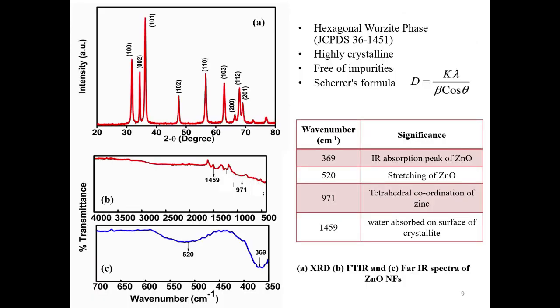This is the characterization technique we have used for the characterization of zinc oxide nanoflowers. We have done XRD. Here is the hexagonal wurtzite phase, which can be confirmed from JCPDS 36-1451. The material is highly crystalline; the sharp peaks show a crystalline material free from impurities, as there is no other peak other than the zinc oxide crystal planes. The particle size was calculated with the help of Scherrer's formula, D = kλ/β cos θ. Here the major peak is 101, from which we can calculate the particle size